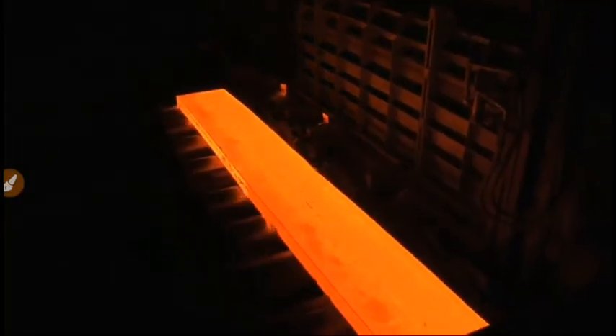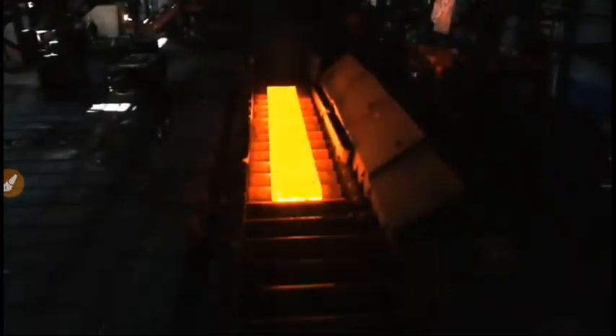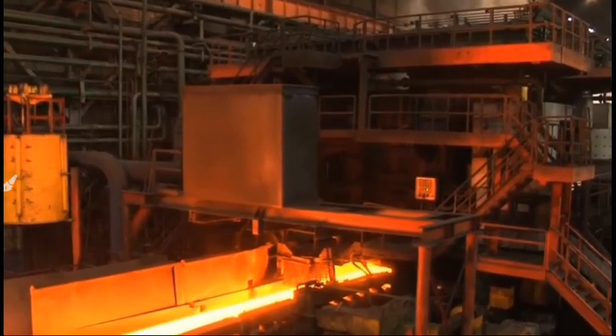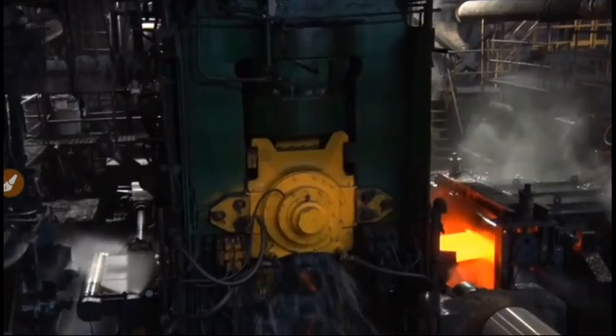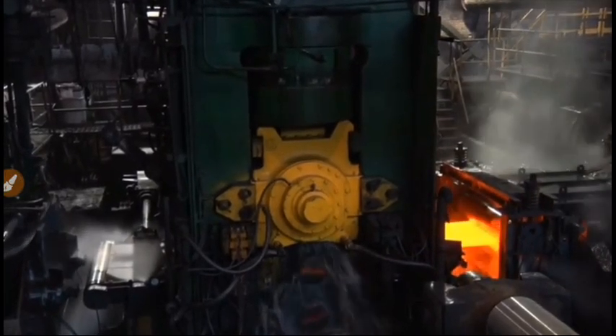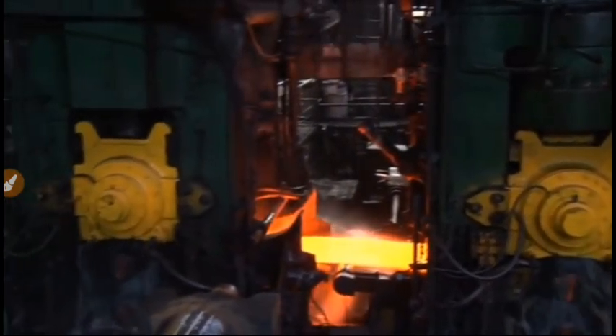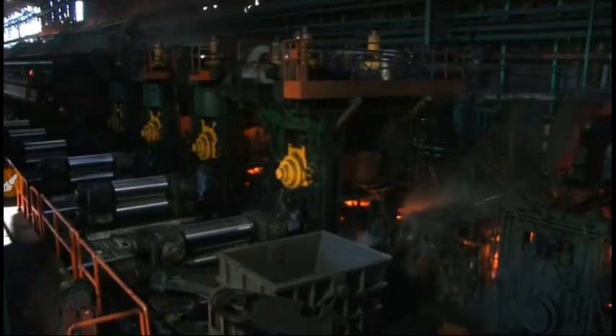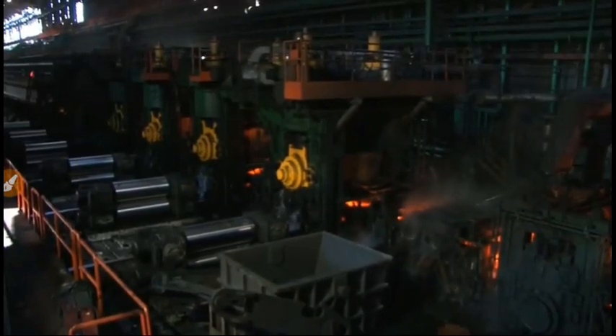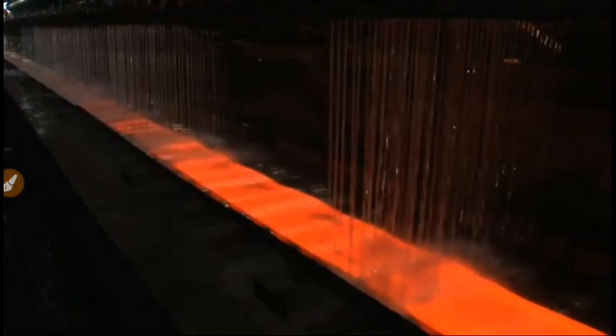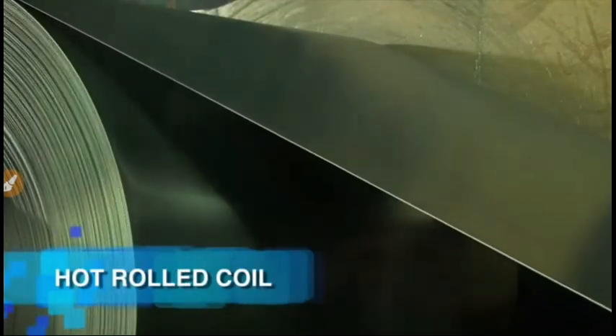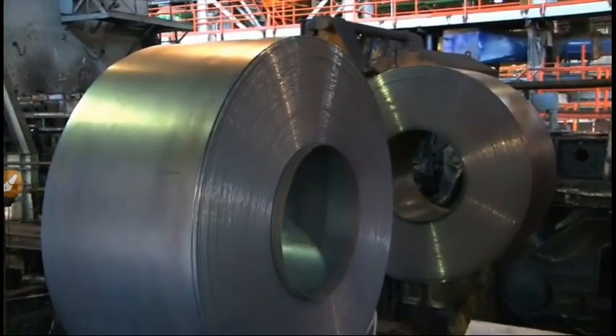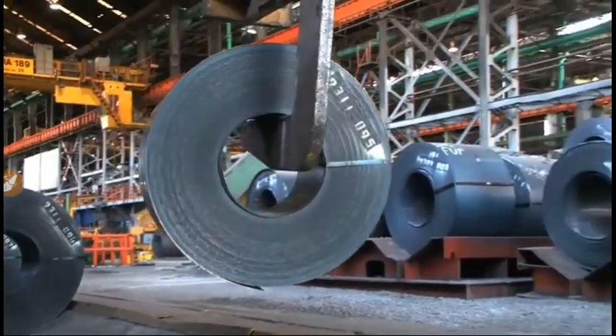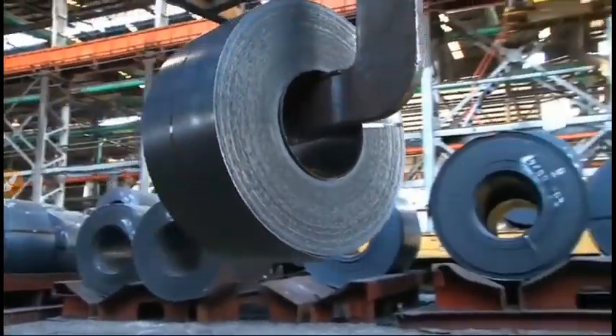On the hot strip line, the slab is processed for the production of hot-rolled coil. First, the slab is reduced in the universal reversing mill to a thickness of 2 inches, and then on the M stand it is further reduced to 1 inch. The final thickness required by the customer is achieved on the 6-stand roll mill train. At the end of the hot strip line, there is a cooling system and a coiler. Hot-rolled coil, also known as full hard coil, is shipped directly to the customer or sent to other processes in the AHMSA cold rolling departments.